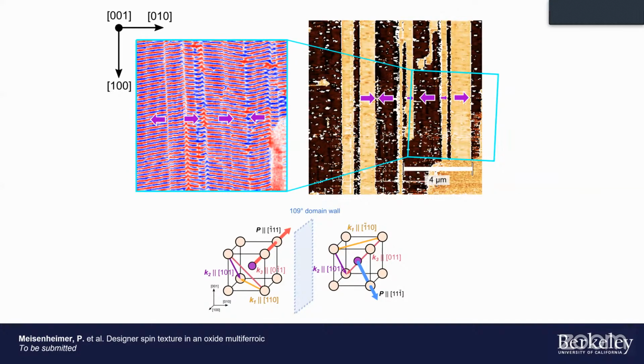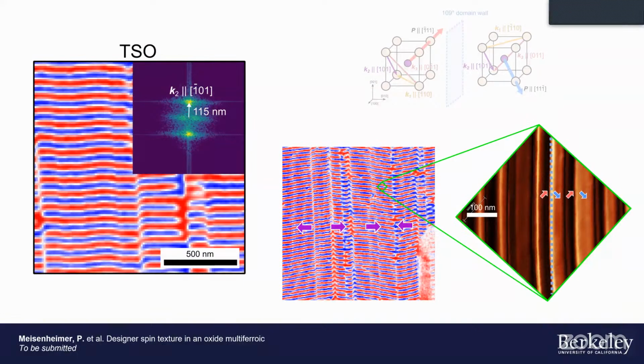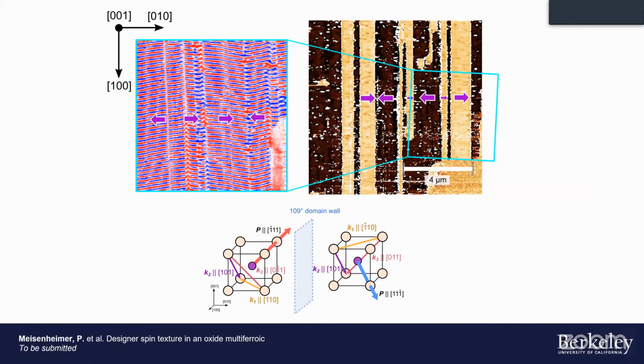In these 109-degree domains, we should stay on this slide for a second. These domains are very fine, but when they zigzag this way, they have a net polarization that's pointed to the right. Globally, you can have families of these domains or macro domains where you have a zigzag with a net polarization that's pointed to the right and a different macro domain with a zigzag where the polarization is pointed to the left. Still 109-degree domains, but instead of this configuration, you have the exact mirror of this, where it's up and to the left and it's down and to the right.